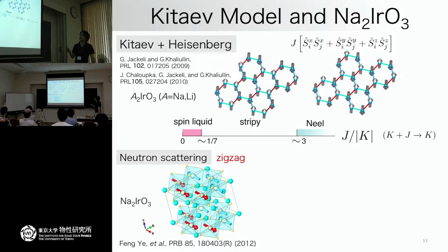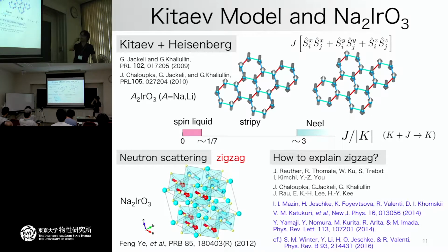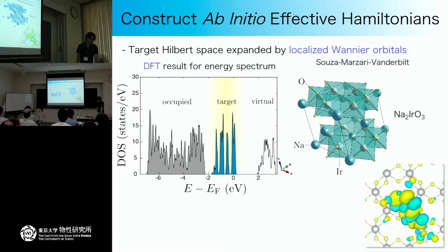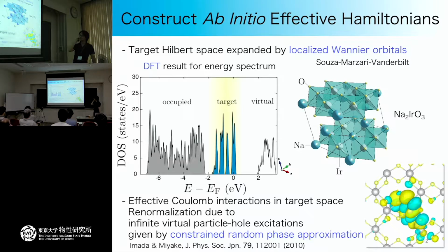So around 2010, there was much discussion about sodium iridate, because if you do the neutron scattering, then people found that there is a zigzag magnetic order. Here you have a zigzag chain with ferromagnetically ordered spins, and it's coupled with the neighboring chain in an anti-parallel fashion. However, this kind of order cannot be found in the phase diagram of the Kitaev-Heisenberg model if the J is positive and the K is negative. So there are many debates, and we're also working on these topics with the ab initio Hamiltonian. And here, just in case, I prepared a slide to describe the ab initio effective Hamiltonian, but I will skip this part. If you're interested, then please ask me a question.